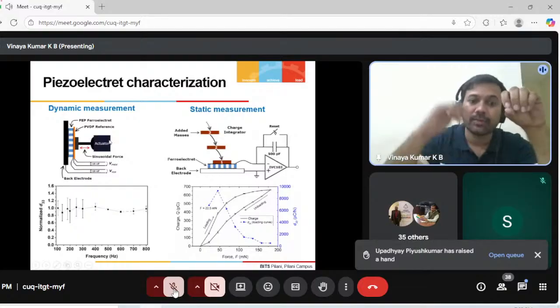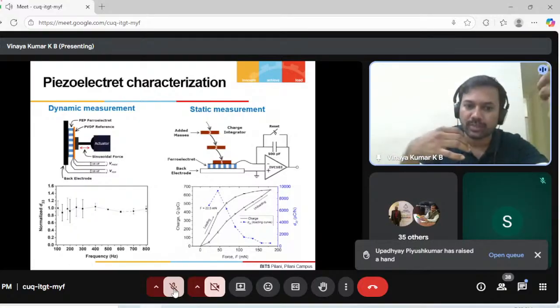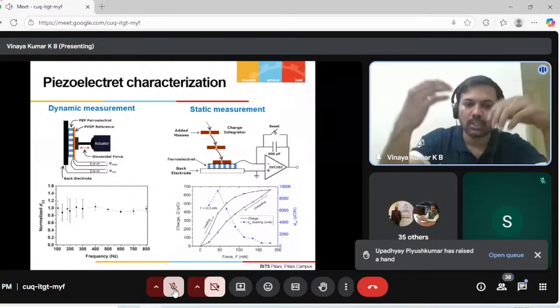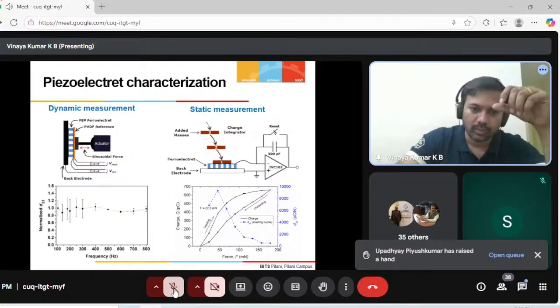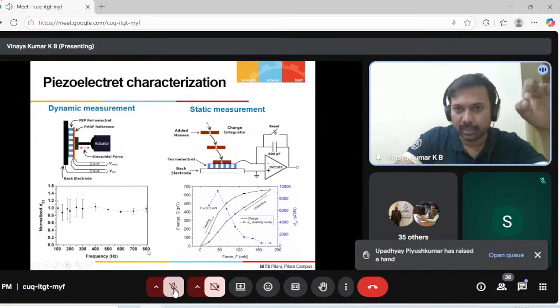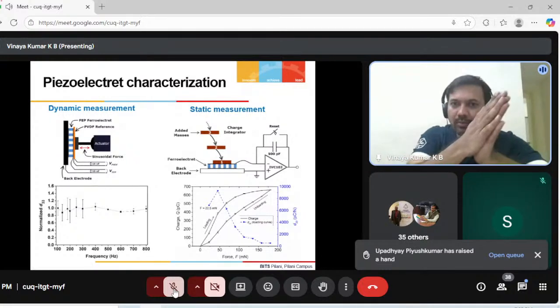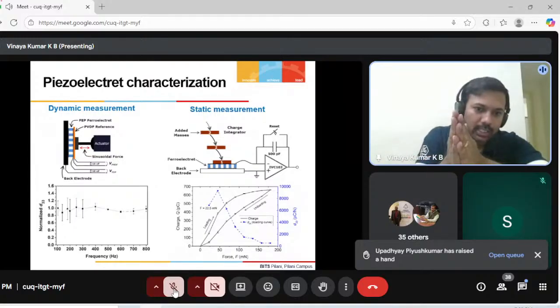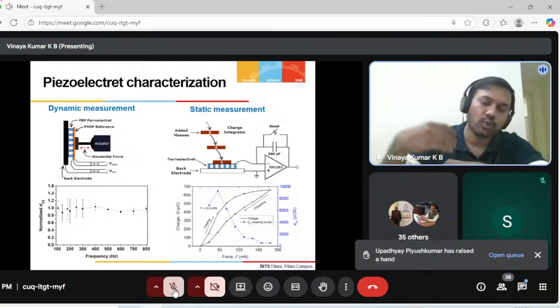This is the sensor at different frequency, how it responds at low frequency and high frequency, and then how the D33 will vary. So we're able to show that whatever the D33 we generated, the sensor is able to work as high as 800 hertz. So not just the low frequency, but it can also be used at high frequency as high as close to 800 or 1 kilohertz.